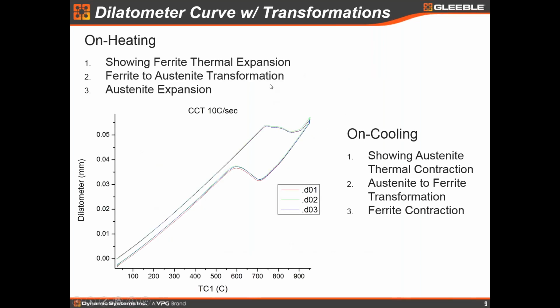Of course, if we go to a material that has phase transformations, we get a little more complex plot. This is a simple dilatometric curve. Actually, this is three curves laid on top of each other. So three different experiments with three different samples. So very good repeatability here. This is a low carbon steel cooled at 10 C per second. And I don't know what the heating rate is, probably about 10 C per second as well.